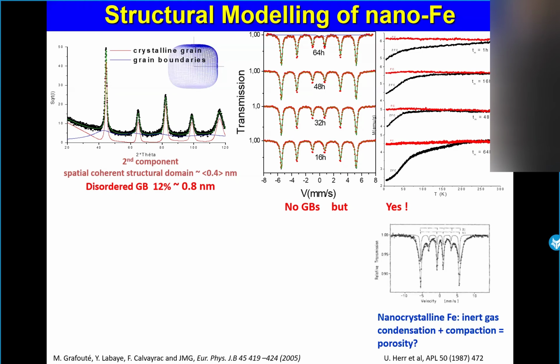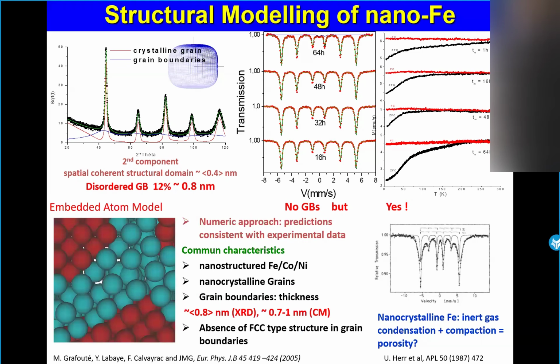Okay. So this result was different from that of the group of R in Hull, where it was possible to see different components, but the structure was also totally different. So we used a computer, and the idea was to push a few blocks in order to get a minimum of energy. And the main characteristics at the end were the nanostructure. The size of the grains was rather similar to that observed by Mössbauer, because it was possible to estimate finally the content of grains by X-ray diffraction, the size, and finally the thickness of the grain boundaries. And the thickness was experimentally 0.8 nanometers, and by computer modeling between 0.7 and 1 nanometer. So the results were very consistent.